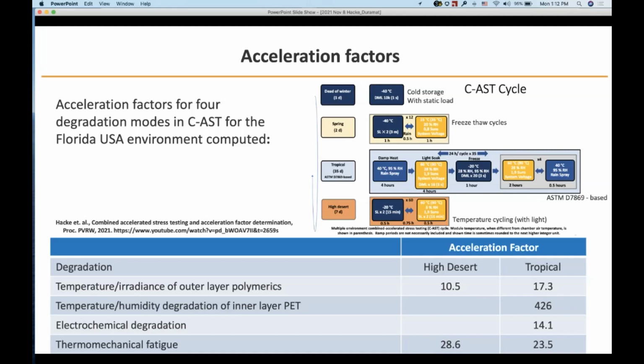And the acceleration factors depend on the mechanism, but it's on the order of 14 for electrochemical degradation, basically electrolytic corrosion, up to 426 for PET. So there's a range, and there's really nothing we can do about that because different degradation processes have different activation energies.